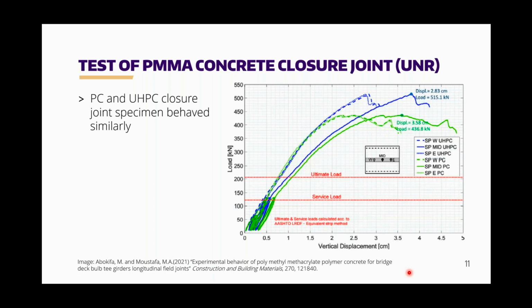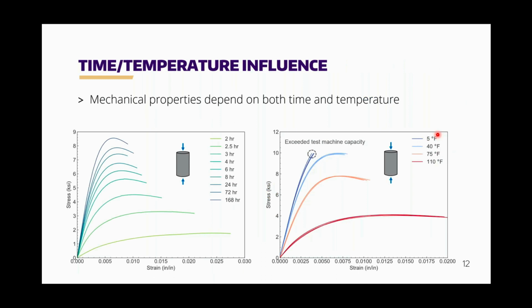The response was similar between the two panels. You can see the dashed and dotted lines are those points adjacent to the midpoint, and the solid lines are the midpoint displacements. So overall, behavior very similar. Did see a slight reduction in strength, but in terms of damage patterns and everything else, the two were quite similar. So both of those tests show some promising results for the use of polymer concrete as a closure pour material.